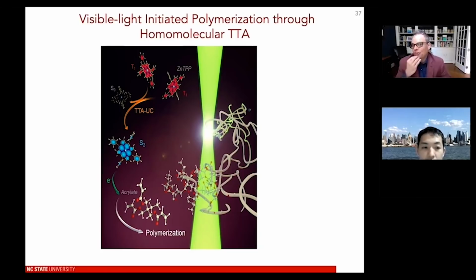If you do the usual acrylate photoactivation with an ultraviolet light source, you'll turn that entire sample solid in seconds. Ooh, I see. But if you do this inefficient upconversion, you can penetrate all the way through and draw the object in effectively three dimensions. Well, you're really not controlling the third dimension because it just goes right through, but you can make a two-dimensional object very easily. And it's more controlled, spatially controlled. That's the real difference.